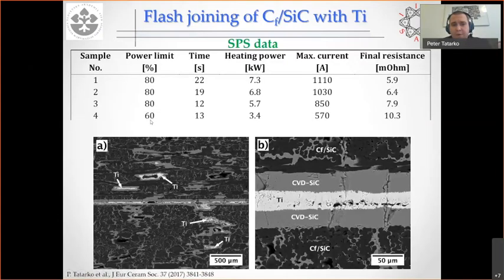We set the power limit to 60%, and we kept almost the same time as in the case before. You can see here, in this case, we didn't see any decomposition of silicon carbide anymore, which was a good sign. On the other hand, the pure titanium foil was again melted, and you see it here far away from the interface. So it was still an issue, but we were sure that we were on a good track.